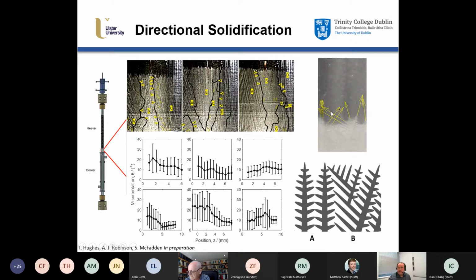So we used the tracking, and we could also track the secondary arms as well. And we've looked here, and it's really because we think there are some particular orientations in 111 growth where the secondary and tertiary arms are just as competitive as the primary arms. So that's, I think, something that's interesting that hasn't really been looked at previously. So the 100 growth will obey the Walton-Chalmers. The 111 growth is selectively disobeying the Walton-Chalmers based on orientation.